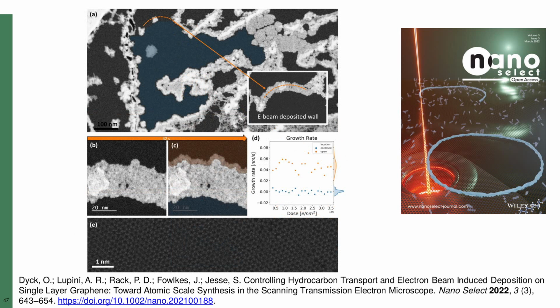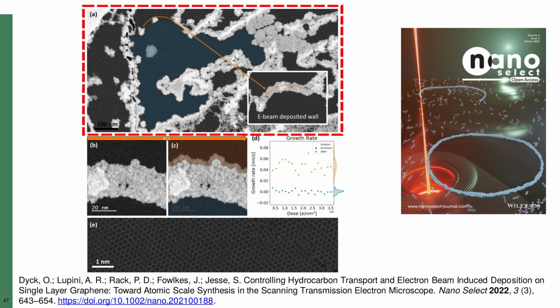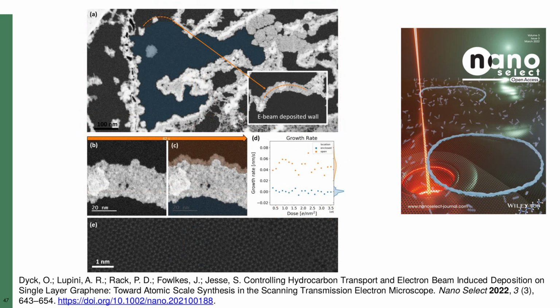To leverage this new knowledge, I selected an area of graphene I wanted to work in that was almost enclosed and deposited a wall to seal it off from the rest of the graphene. I then acquired another video across the deposited barrier and indeed was able to create sections of graphene that remained free of deposition at elevated temperatures.